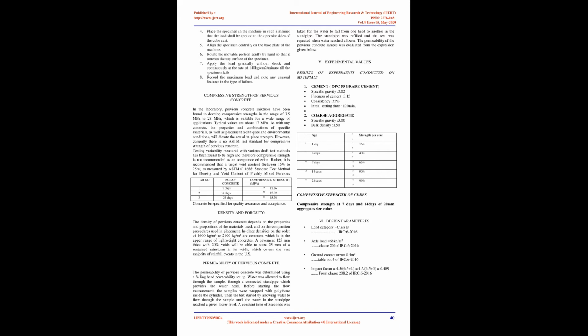2. Take the dimension of the specimen to the nearest 0.2mm. 3. Clean the bearing surface of the testing machine. 4. Place the specimen in the machine in such a manner that the load shall be applied to the opposite sides of the cube cast. 5. Align the specimen centrally on the base plate of the machine. 6. Rotate the movable portion gently by hand so that it touches the top surface of the specimen.